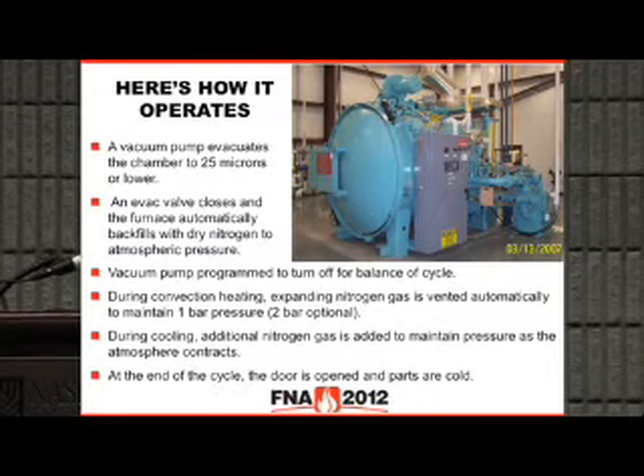And then during the cooling cycle, after the soak is complete, there's a contraction that happens as the gas cools. So as that gas cools, we'll add additional nitrogen for a few seconds, and that'll bring the pressure back up to typically 1 or 2 bar. At the end of the cycle, we'll vent off any excess pressure we might have. Then we'll open the door, the parts are cool, and the load is removed, and you can reload the furnace for your next cycle.